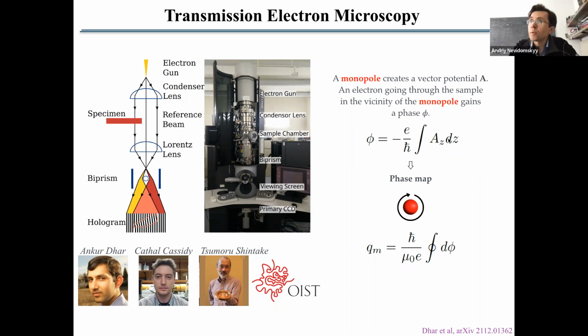Oh, and that's because monopoles actually carry the magnetic charge, right? It's a 3-in, 1-out configuration, if you will. Exactly. That's because the monopoles can really be seen, from the dumbbell model, as a magnetic charge, and the other part of the magnetic charge creates this dipole with a real magnetic dipolar interaction. So the whole magnetic field comes from the fact that dipolar interactions really have a mu0 over 4 pi in front of them. And this mu0 over 4 pi reappears in the Coulomb potential between the magnetic monopoles. So perfect. That makes sense.